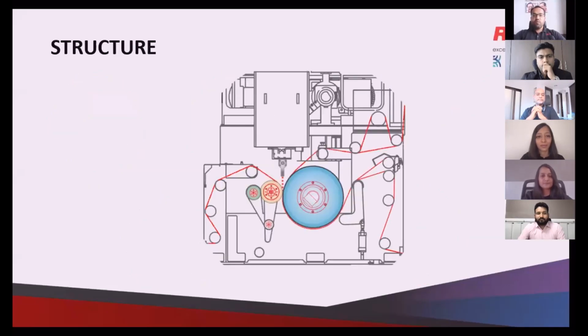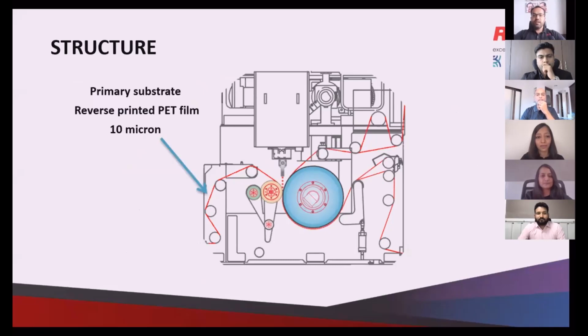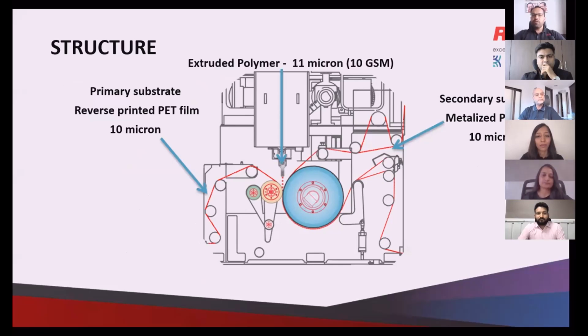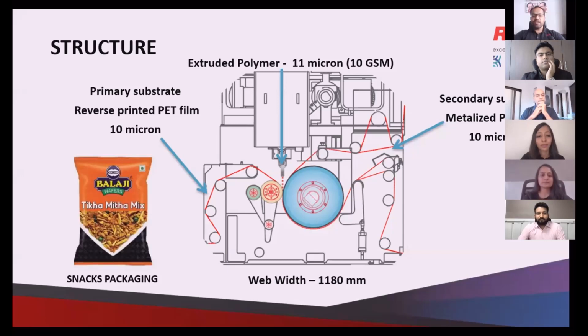The structure we are going to see on this line today is a primary substrate, a reverse printed PET film of 10 micron, laminated with a secondary substrate, which is a metallized PET film of 10 micron, through melt lamination of extruded PE of 11 micron, which is about 10 GSM. The width of the job is 1180 mm and the end application is snacks packaging.